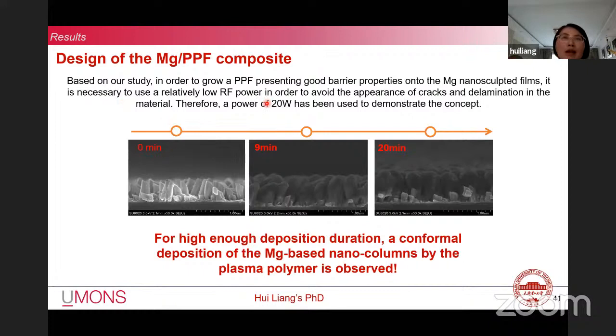Based on our study, in order to grow a plasma polymer ethylene film presenting good barrier properties onto the nanostructured Mg films, it is necessary to use a relatively low RF power in order to avoid the appearance of cracks and delamination in the material. Therefore, a power of 20 W has been used to demonstrate the concept. Then, in the same reaction chamber, the plasma polyethylene coating was deposited on the surface of the nano Mg film.